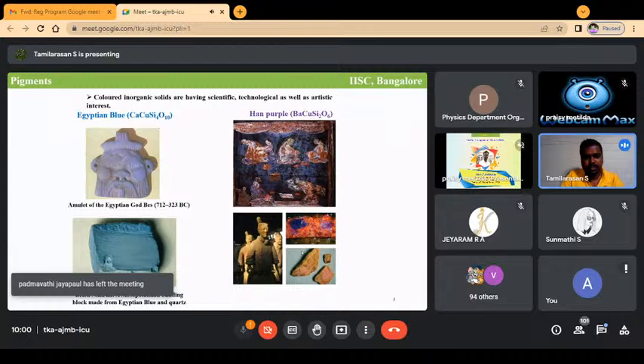So what we did basically for my PhD thesis was take a material that has no color, in the sense it's white, having a band gap more than say 4, and dope some transition metal ions which are partially filled, that would give rise to electronic transition between valence state and conduction state and create colored materials. When we went through the literature survey, we found a very interesting material, YInO3, where indium is 5 coordinated and indium is in 3 plus. When indium is substituted with a little bit of manganese 3 plus, it gives a very beautiful blue color, which is interesting because manganese 3 plus always has dark color, band gap less than 2 electron volt. But how can this happen?